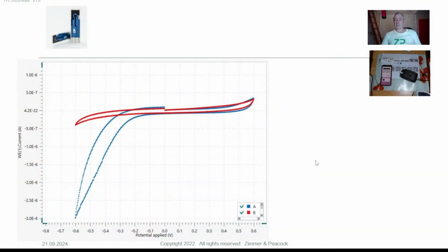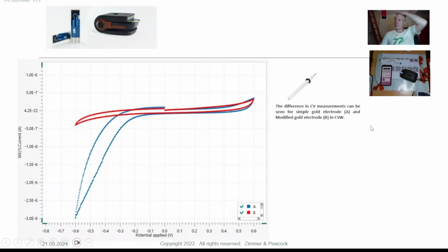But let's get back to the main thrust here. The nice thing about ZP and these weekly webinars is we will cover technical questions that come in. First thing to say is this is done on a gold electrode, and they describe it as a simple gold electrode and a modified gold electrode. This discontinuity in the data is no big problem. Sometimes when you read academic papers, you don't see this discontinuity because they show you the second scan, or they may start the voltammetry at open circuit potential.